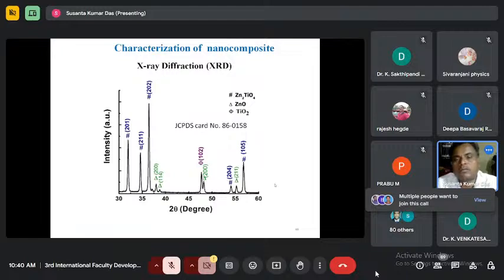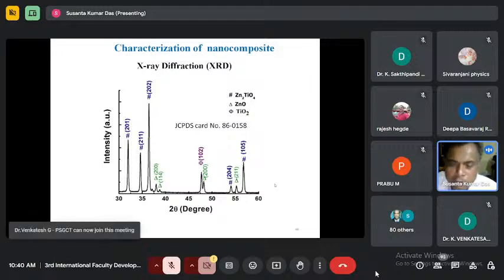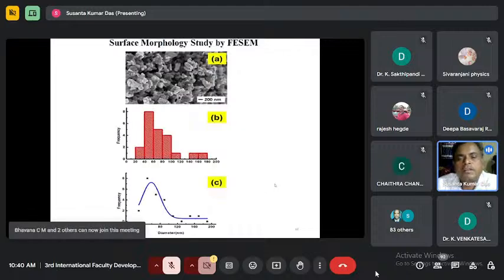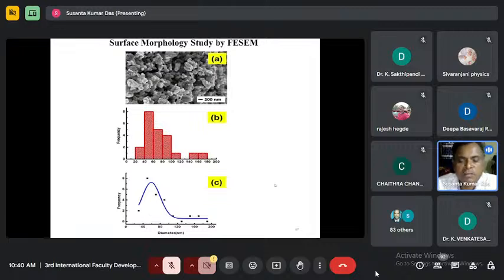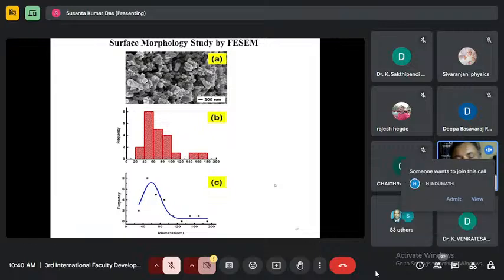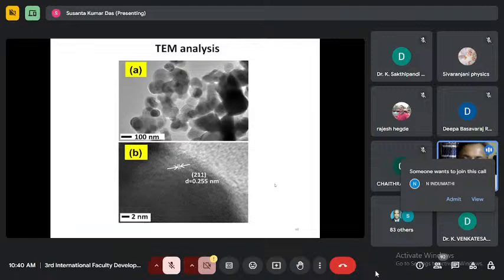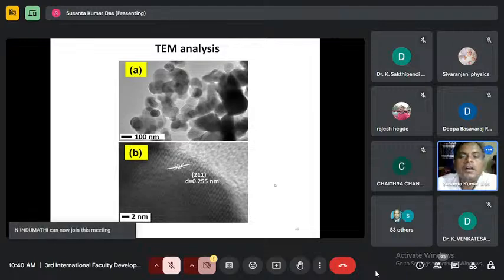Then we found a significant amount of zinc orthotitanate peaks, but residual zinc oxide and titanium dioxide were also found in our materials. Generally, it's very difficult to really go for 100% conversion of the materials. Then we went for the particle analysis, and the particles were within 50 to 60 nanometers, which was already confirmed through TEM.